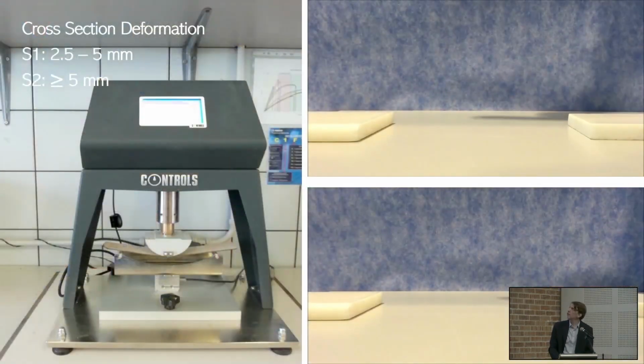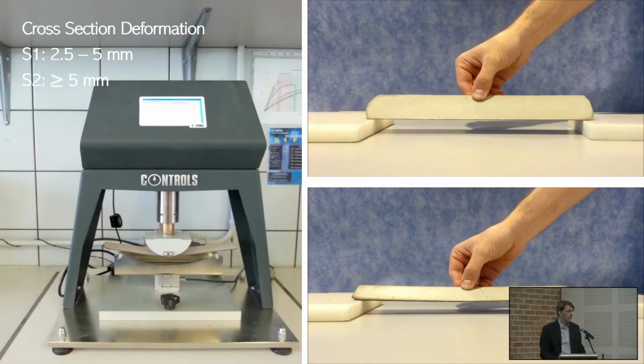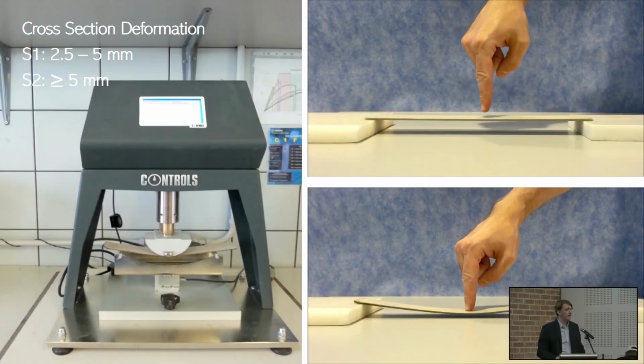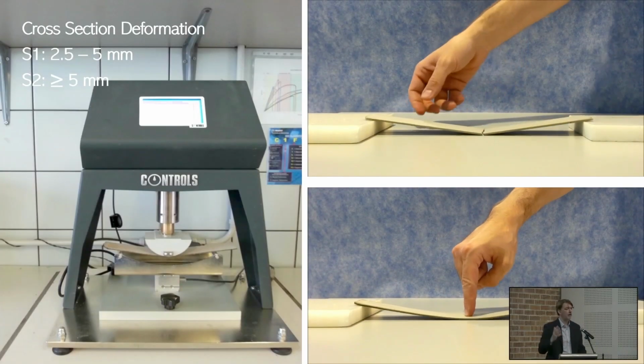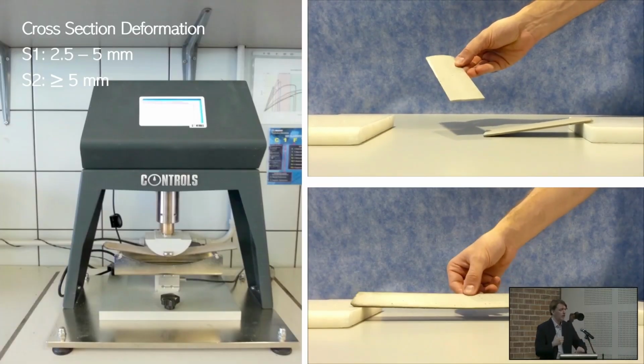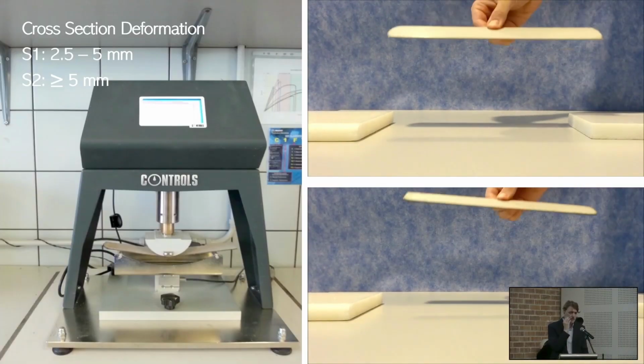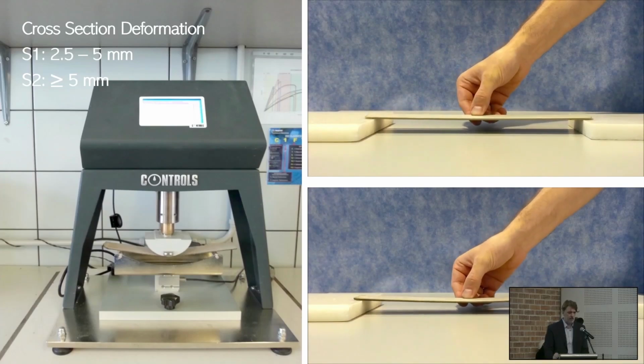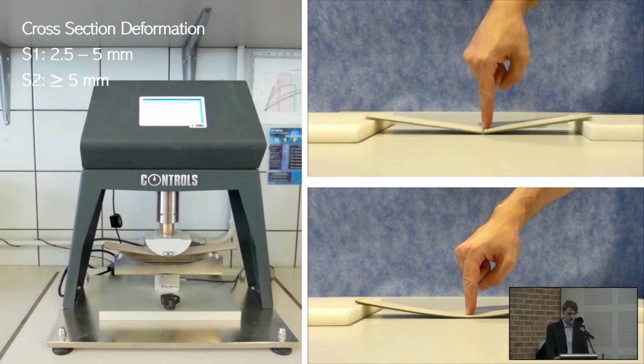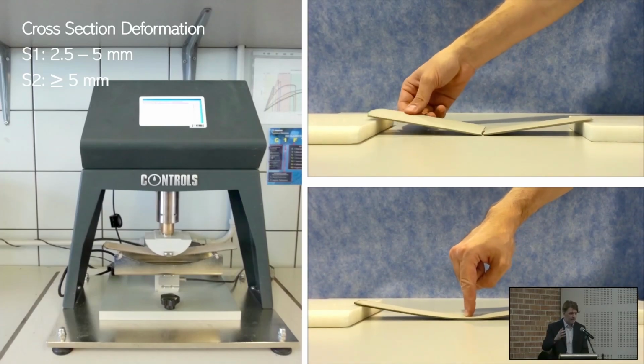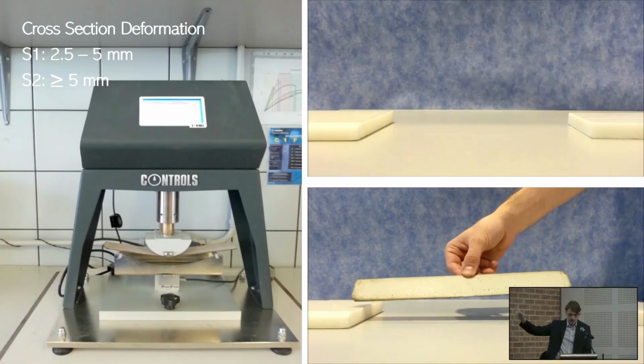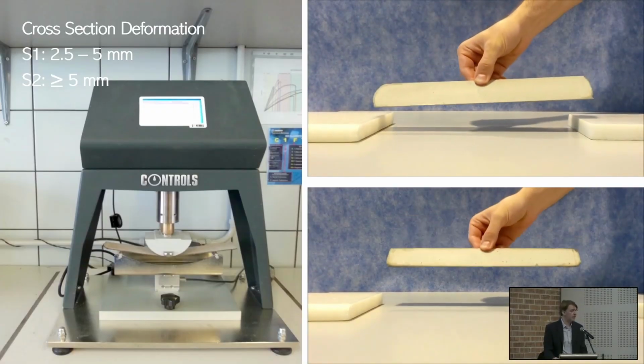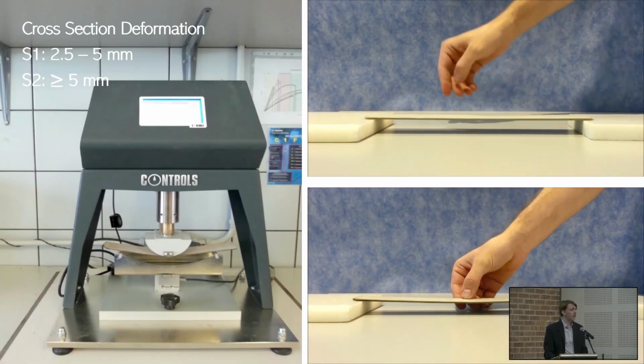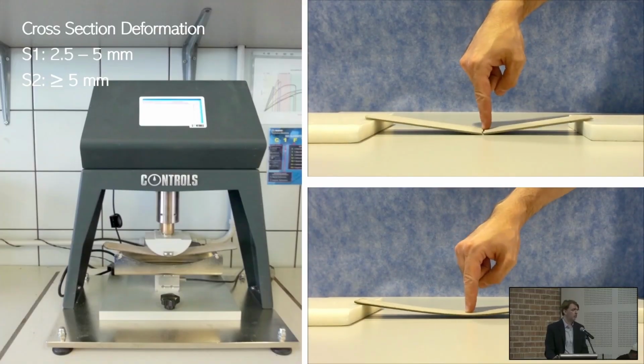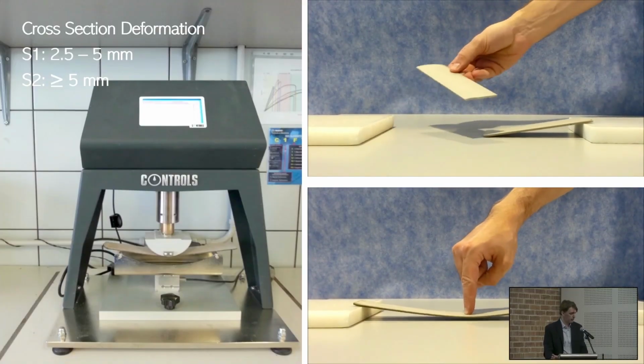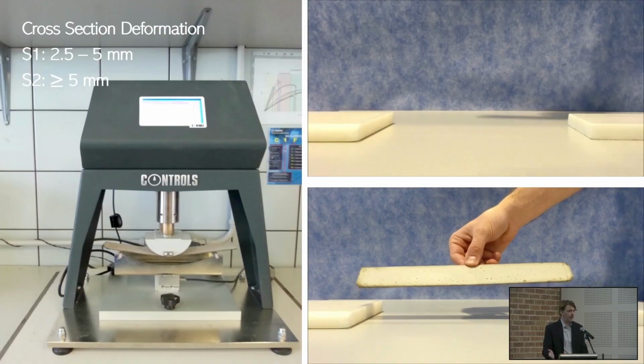But I want to focus on the deformation of the adhesive. You remember we said that the tiles, especially the big tiles, can have a certain movement. So when I fix this kind of material, maybe the deformation of a cement-based adhesive can be an interesting characteristic. Some adhesives are not deformable, as you see at the top. Some others are deformable, and the international standard divides them in class S1, S2. Class S1 between 2.5 and 5 millimeter deformation, class S2 over 5 millimeter.